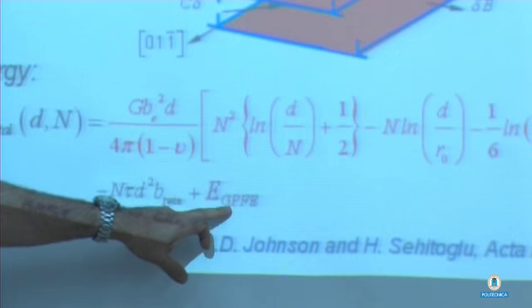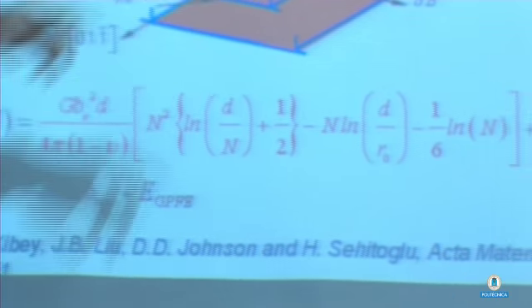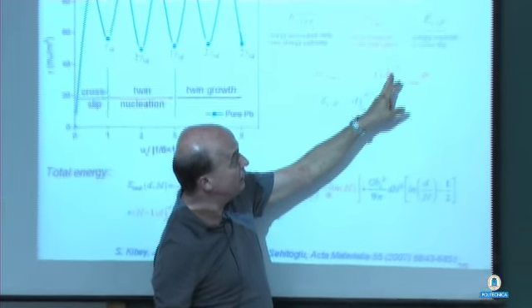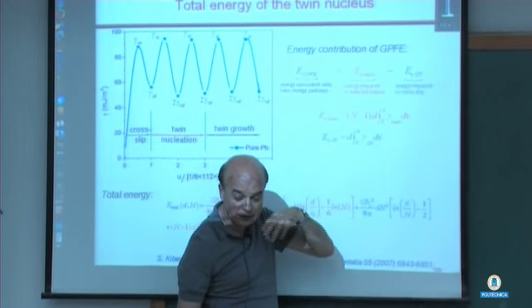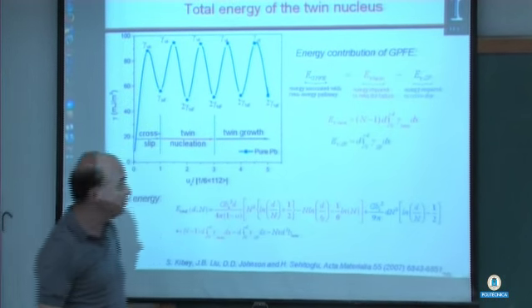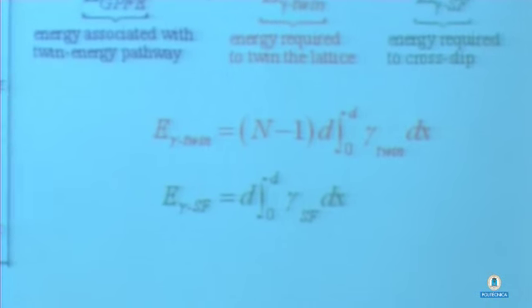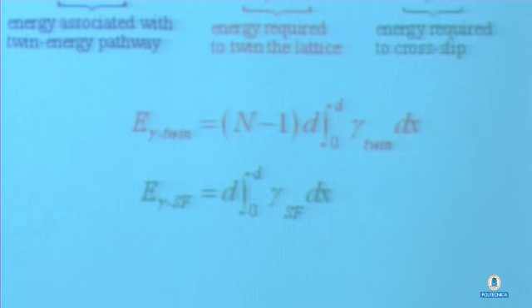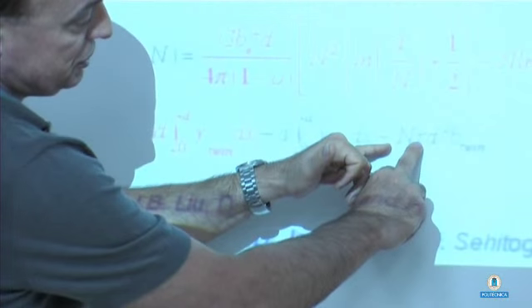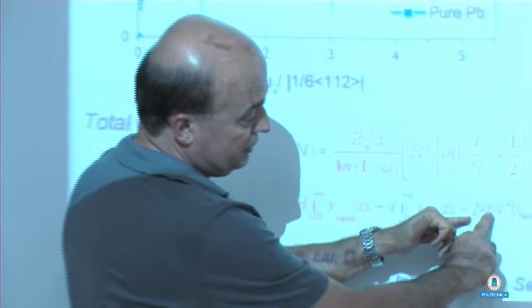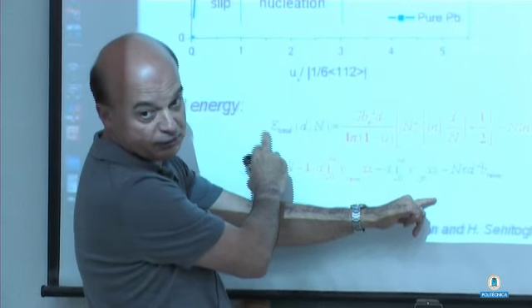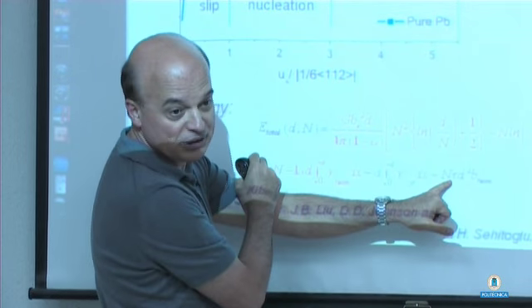That's the applied work done due to applied stress, and that's GPFE, which is shown here. It's basically the integral of the generalized plane fault energy curves. And so you can write the total energy expression again. This is the GPFE expression. This is the applied shear stress here. But we're going to minimize this and try to establish the twinning stress.